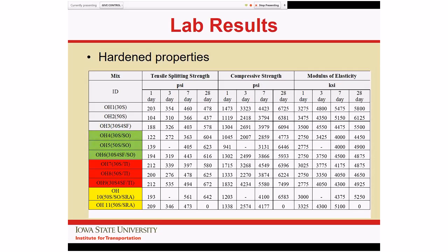One other thing to note on this contract, we did include as part of the addendum that added this note an item for the shrinkage reducing admixtures. When we took a look at that, based on the lab data that we had and based on the cost of it, there were some other factors being introduced there that might be problematic. So we did decide to non-perform that and not use the shrinkage reducing admixtures for a number of reasons.